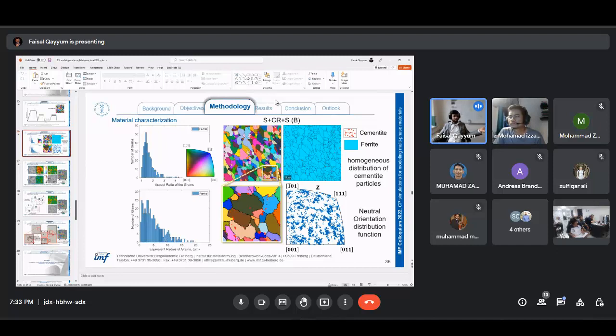And then we were also using it to clean the data and export this EBSD as a text file, so it can then be constructed into a geometry file by DAMASK. So we are also using MTEX to export text data from this file in such a structure that it is readable by DAMASK and can be converted into a geometry file. So then we are using MTEX for all these different reasons: to post-process the EBSD data, to statistically analyze this data, and then to export this data into our desired formats.